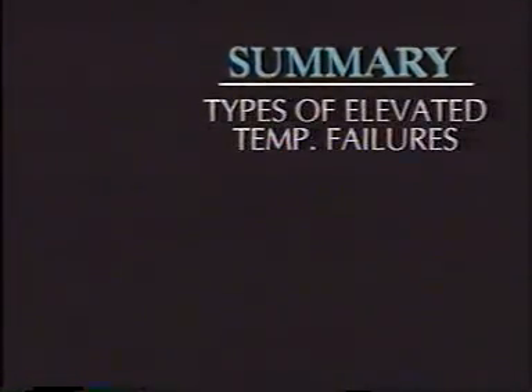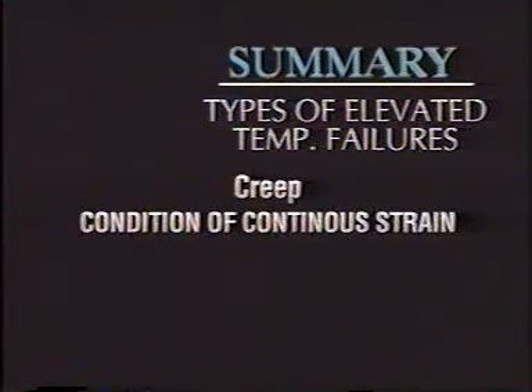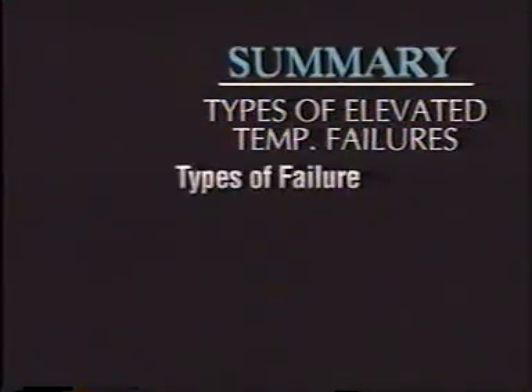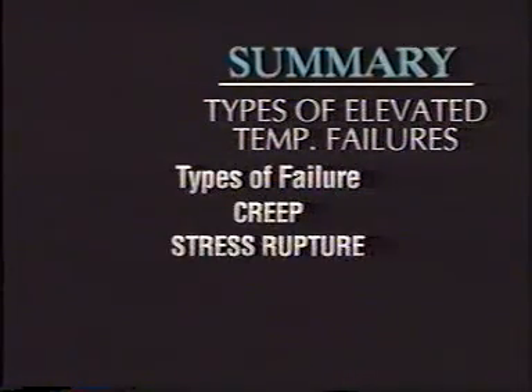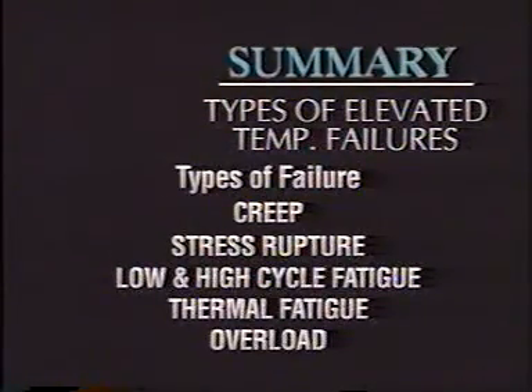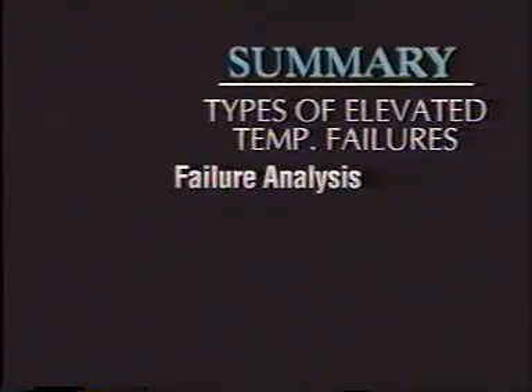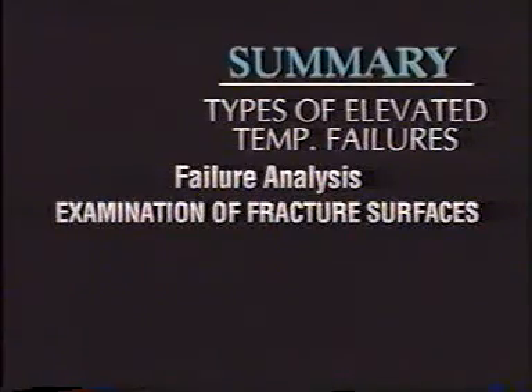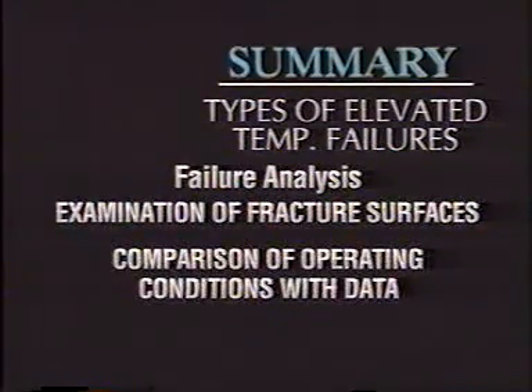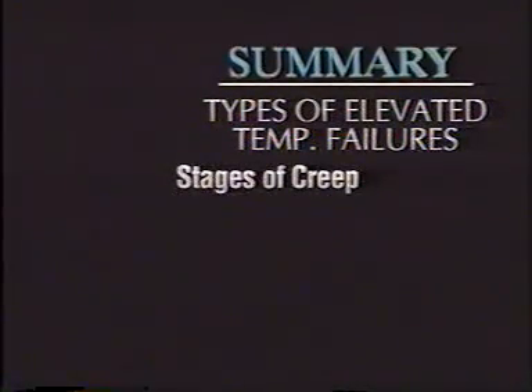Summary: types of elevated temperature failures. At elevated temperatures, stress produces a condition of continuous strain, creep. Principal types of failure are creep, stress rupture, low and high cycle fatigue, thermal fatigue, and overload. Type of failure is established by examination of fracture surfaces and by comparing operating conditions with available data on elevated temperature fractures. Creep occurs in 3 stages.